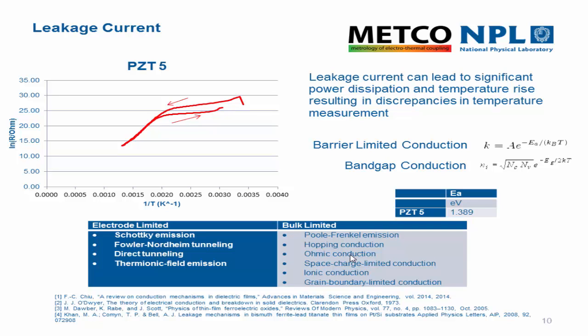And so you can see here, this is a PZT disc, measuring the resistance as a function of temperature. This is 1 over temperature on this scale, and this is a log scale on the resistance. So we can see that once we get above a few hundred degrees Celsius, then the resistance drops linearly on this log scale. So the conductivity increases very rapidly as we heat these materials up. There's quite a lot of work in the literature that's been done on conduction mechanisms and the contributions from things like vacancy mediated processes or even direct band gap conduction.